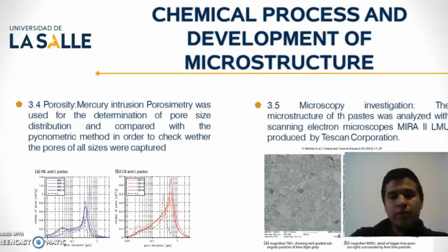Mercury intrusion porosimetry was used for the determination of pore size distribution and compared with the pycnometric method in order to check whether the pore sizes were captured. Different behavior was found, where the interaction between the lime and crushed brick particles was not detected by EDX mapping, which documents the composition of lime grains consisting of calcium only, while the elemental composition of brick grains is based purely on silicon and aluminum.